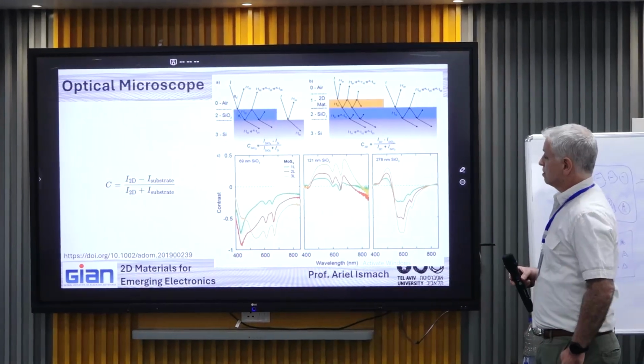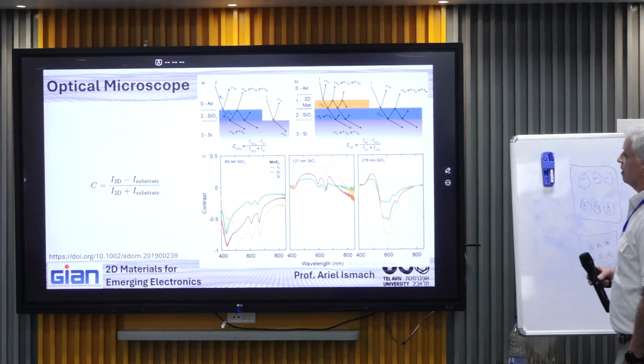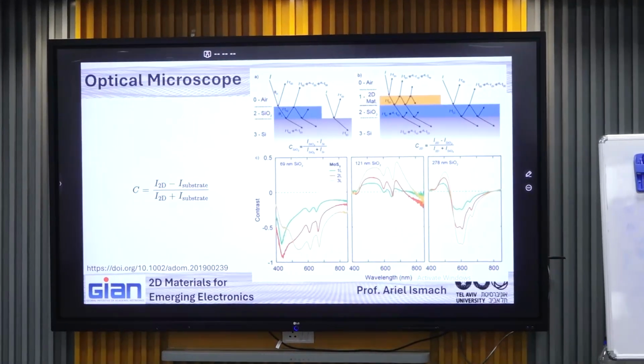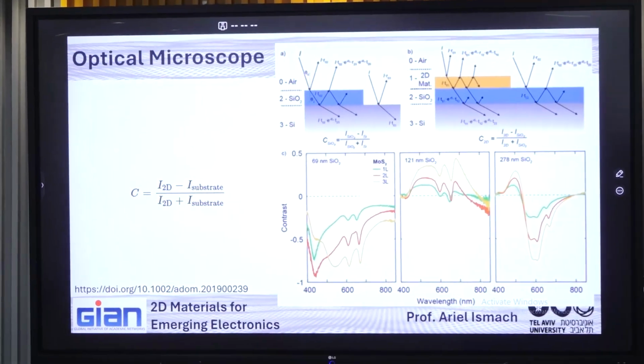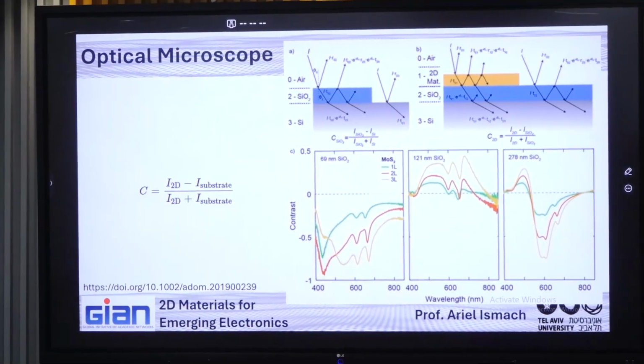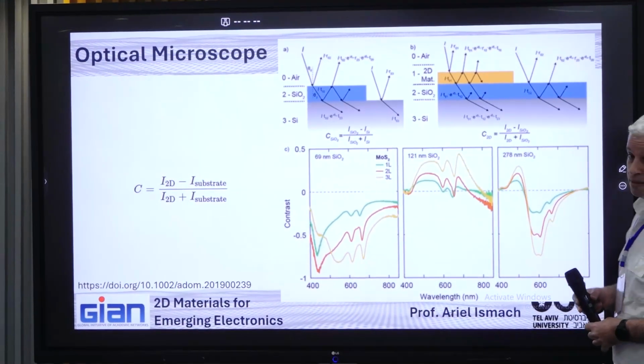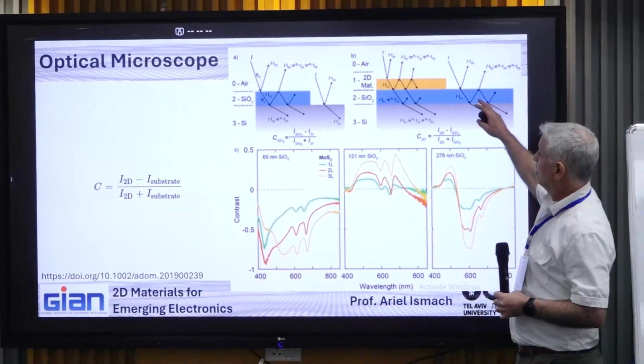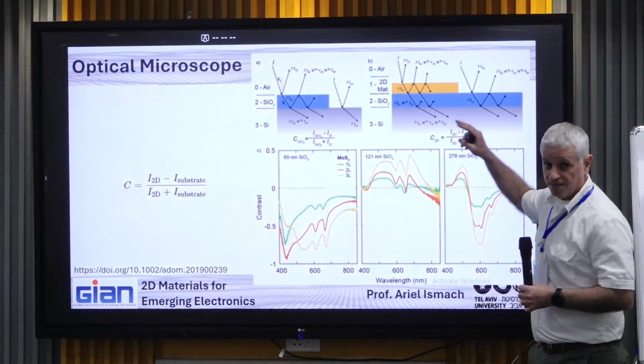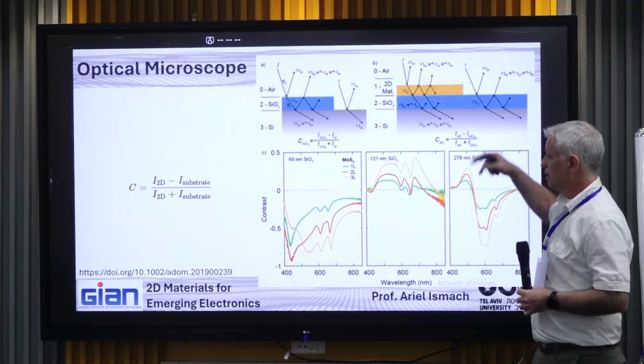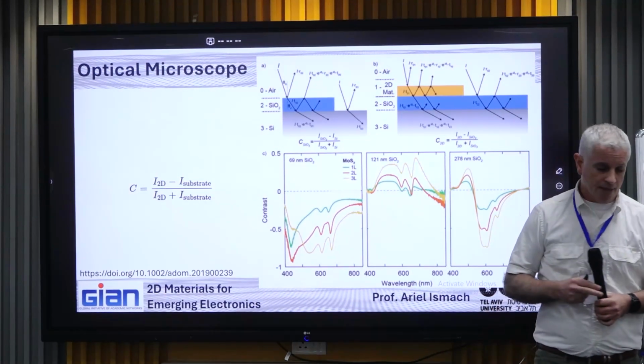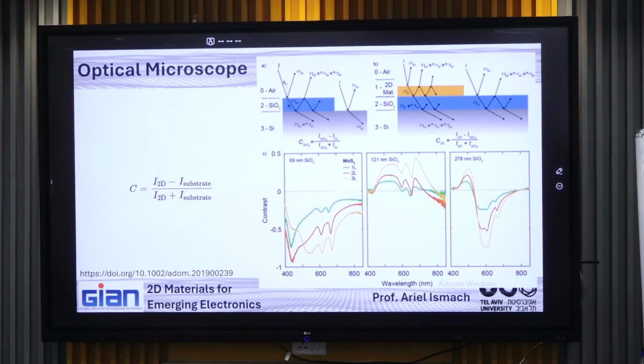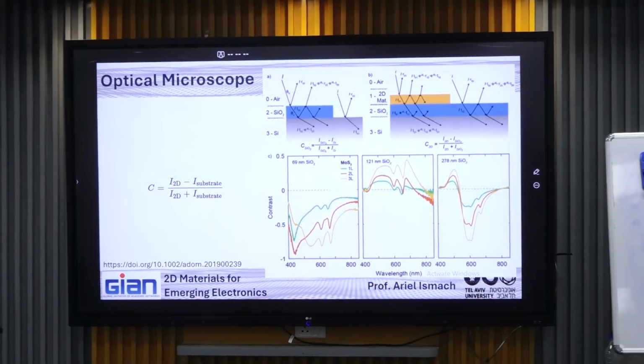And how it works, there are many papers describing that. Basically, the contrast calculation is a bit complicated because we are talking about thin materials lying on top of a silicon dioxide layer with a specific thickness on top of the silicon substrate. Of course, the contrast that I showed you was for the silicon dioxide silicon wafer.